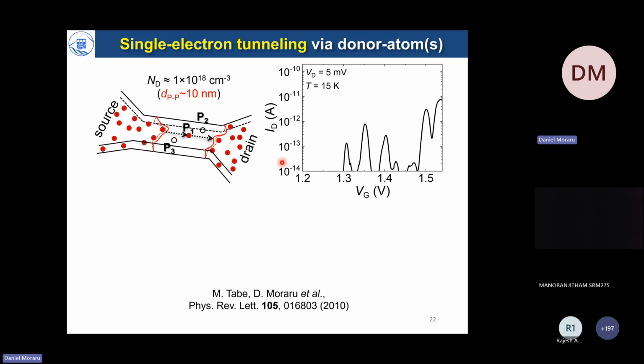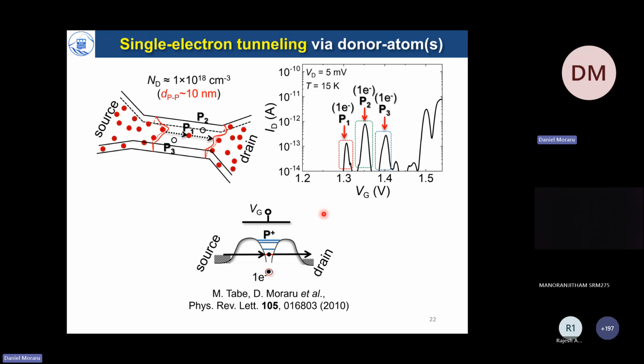So when we do that, we can observe in many cases, although different from device to device, current peaks, as I explained before, and these current peaks can be ascribed to different phosphorus donors. Now, each of these phosphorus donors carries the current by single electron tunneling, mainly through its ground state, and shuttling the electron towards the drain in sequential mode.